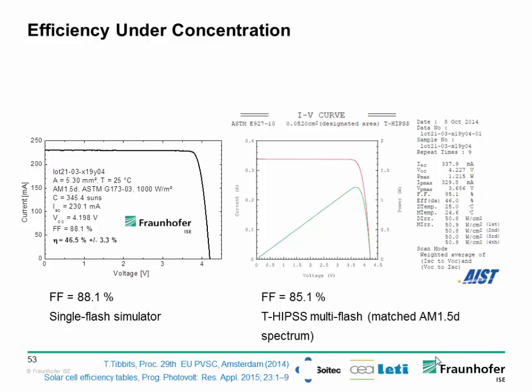These are the world record efficiencies for any photovoltaic device. It was measured here at Fraunhofer with an efficiency of 46.5%, and I draw your attention to the uncertainty, which is there because these very difficult devices are very difficult to measure. And it was also measured at AIST independently, showing an efficiency of 46%, so this is very well within the uncertainty.